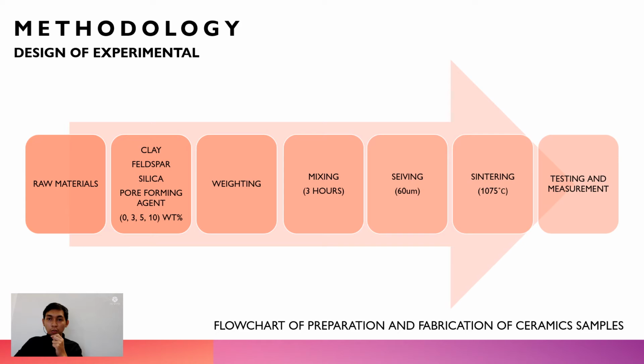For methodology, design of experimental. Here, as you can see in this slide, there is a flowchart of preparation and fabrication of ceramic samples. First thing that we are going to do is collecting all of the raw materials, which consist of clay, feldspar, silica, and pore-forming agent, which is polypropylene. The polypropylene will be added at a certain level of content, which are 0, 3, 5, and 10 weight percent.